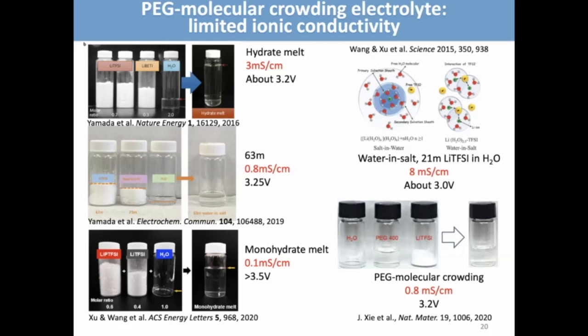So far the PEG molecular crowding electrolyte has been effective in providing a wide voltage window with a low concentration of salt. However, its ionic conductivity is not satisfactory. It's around 0.8 millisiemen per centimeter, which is much lower than the 21 molar lithium TFSI in water. And why is that?